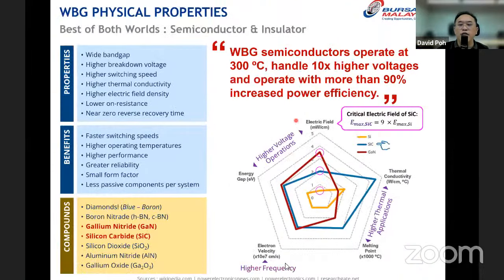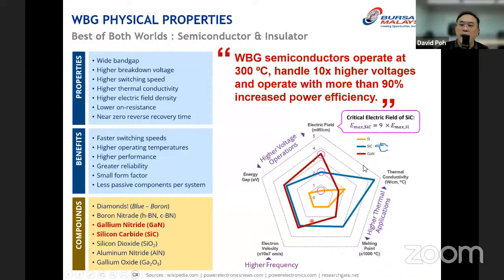Then other than that, because of the higher electron velocity as well, silicon carbide as well as gallium nitride are much better at delivering faster switching speed as a semiconductor compared to the silicon. As well as other properties like a much higher thermal conductivity, which means that the wide band gap materials can operate in a much hotter environment, and plus because of the high thermal conductivity, they can dissipate the heat much better than the silicon.